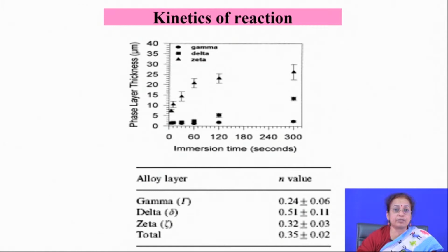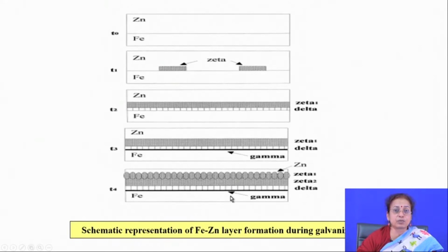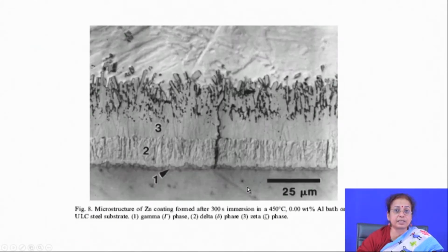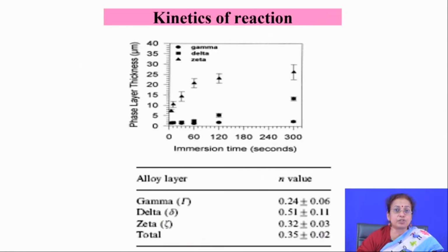If you see the kinetics of the different phase formation, you will find that they have different kinetics. For example, gamma phase kinetics is the slowest. Gamma phase forms at a much slower rate than the delta phase and the zeta phase. From the layer growth itself, you can say that gamma phase kinetics is quite low. It is there at the interface, but zeta and delta phase formation kinetics is quite high, so they form at a much faster rate. So, the kinetics of different phase formation is also equally important; they have different rate values.